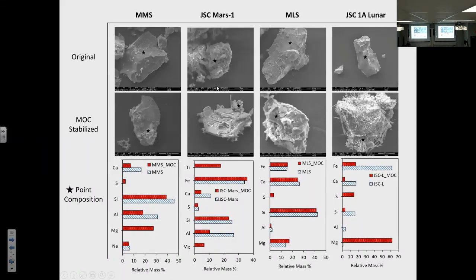So this is where we start looking at our SEM micrographs. In this slide, our first row shows you the original sample without any treatment. The second row shows you images of the magnesium oxysulfate cement stabilized samples. And then the third row shows you the EDS determined elemental composition that corresponds to the little tiny black star that you see on each of these images.